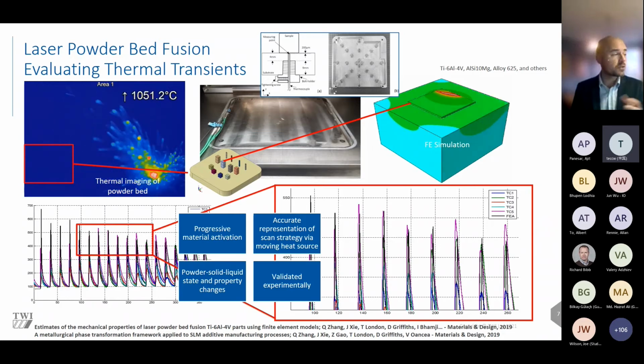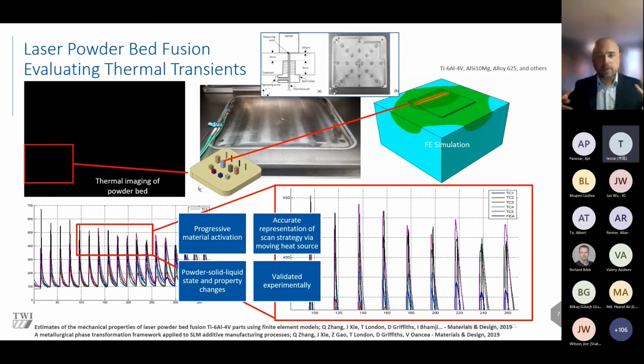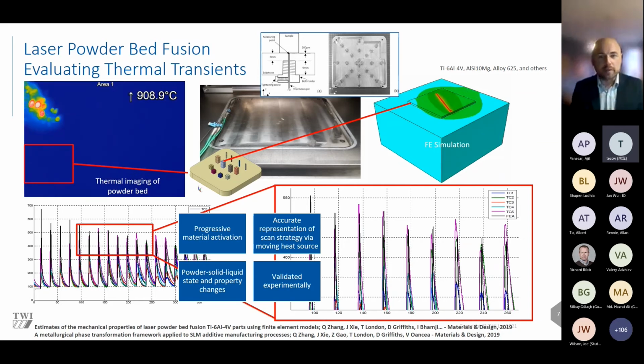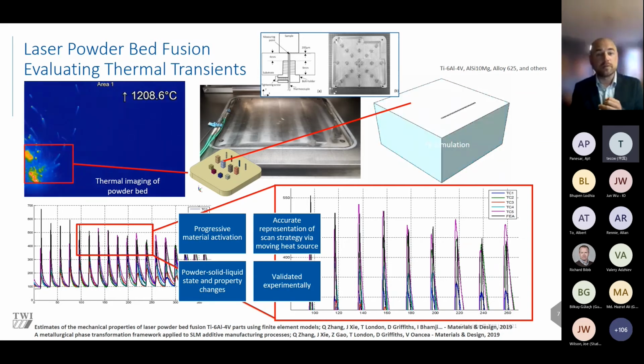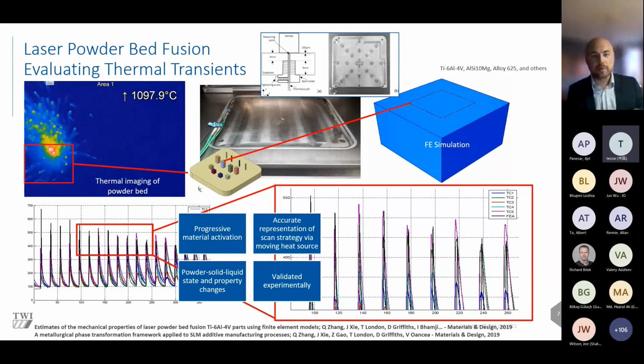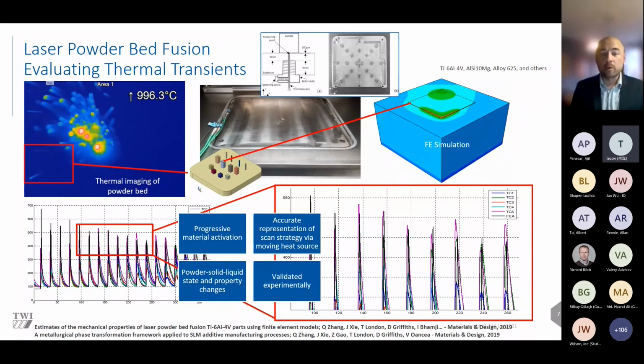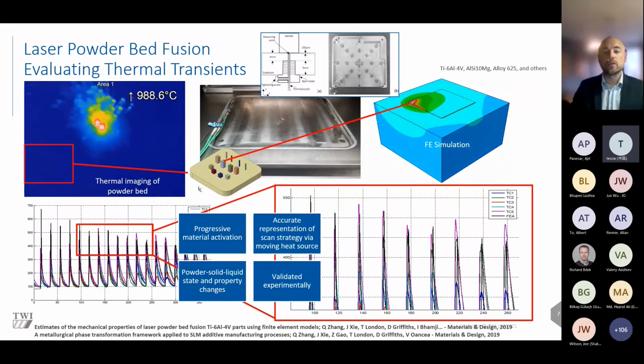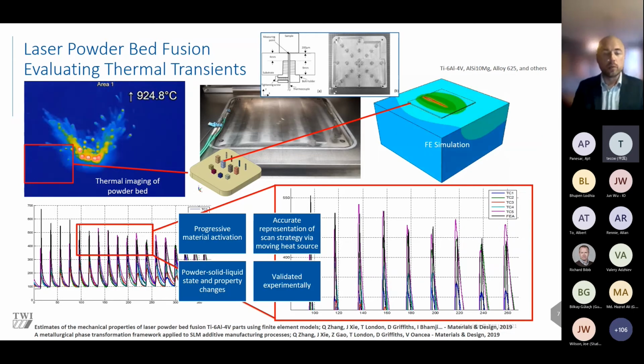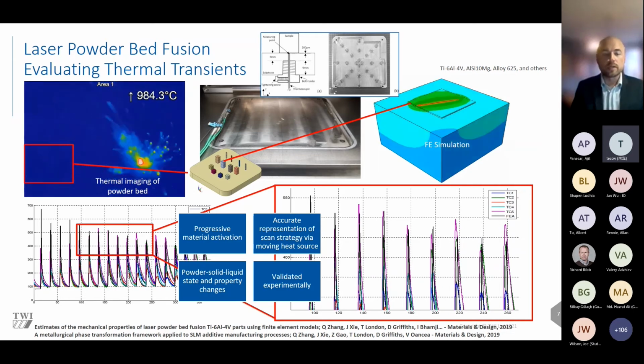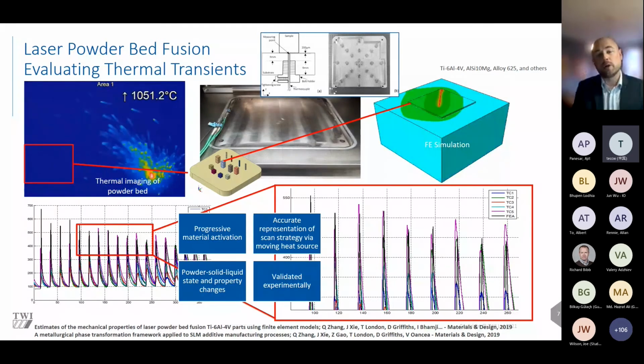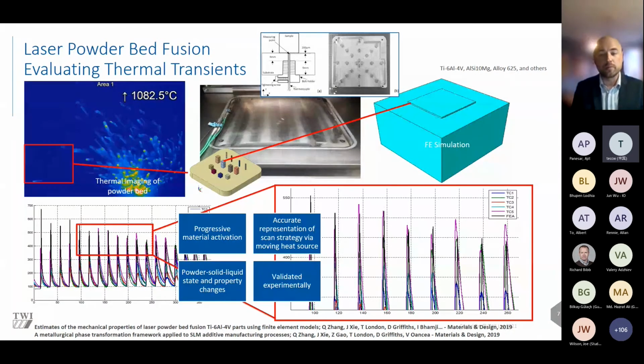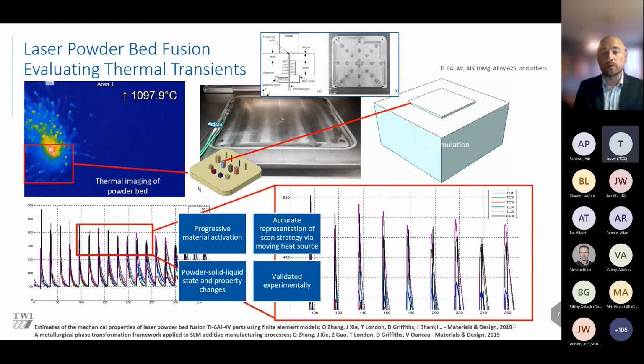real world. So for powder bed fusion, we've designed some substrates that we can thread thermocouples about 200 microns or less below the build surface. And then we can feed the wires out through some excess powder overflow pipes in the machine, in this case, a Renishaw AM250. And we can collect thermal data that we can then use to compare against our model. And we can use thermal imaging as well to look at the sort of ejection of particles and energy loss and the size of melt pools. And through calibration activities, representing scan strategies with high fidelity, we can gain confidence in that thermal model.